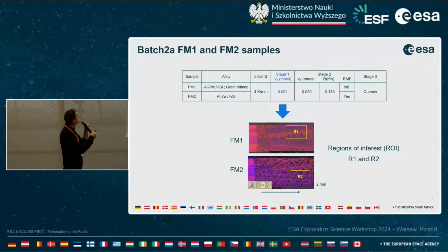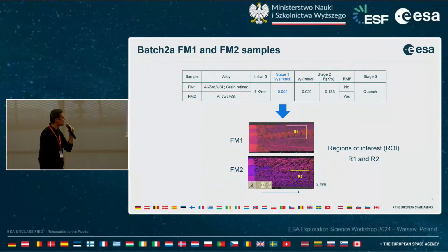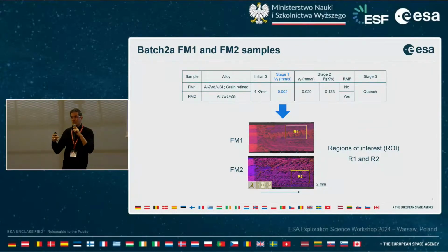I will start with a rather old experiment, batch 2A. For this batch we retrieved the sample, I think, in 2017, the last samples. And it was on an aluminum silicon alloy. We have been studying CET, so there are a number of publications on these experiments. But here I will focus on a recent analysis carried out in these two regions, which are in the columnar area. Here you can see pictures of the columnar part that was solidified in microgravity.